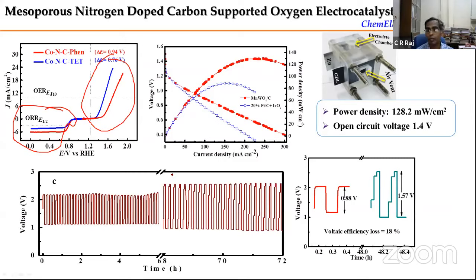Yeah, we made it. We made the homemade Zinc Air Battery, and we tested it. You cycle it up to 72 hours, right? Charge, discharge. I mean, cycling: charge it, discharge it, charge it, discharge it. You could get an open circuit voltage of around 1.4 volts, but it's a little short of the theoretical voltage. The theoretical voltage, as I have shown, is 1.65. Here it is only 1.4.